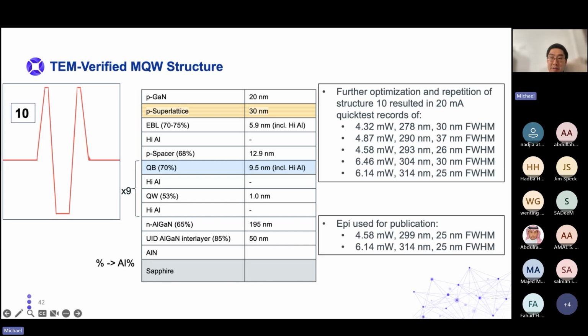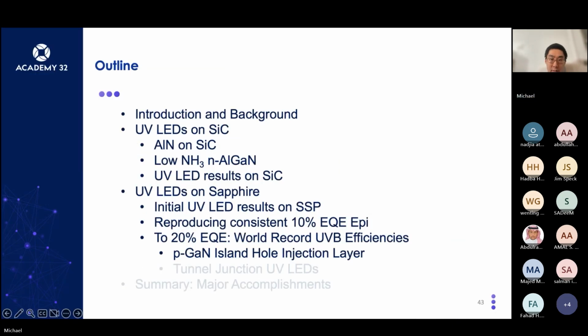So the wall plug efficiency doesn't correlate to this, because in the publication we just measured the efficiencies with the indium contacts that we use for quick test because of fabrication difficulties. With further polishing of our fabrication process, we will definitely get better voltages, and those wall plugs will meet up better with external quantum efficiencies. So to 20% EQE, that is what I was just talking about.